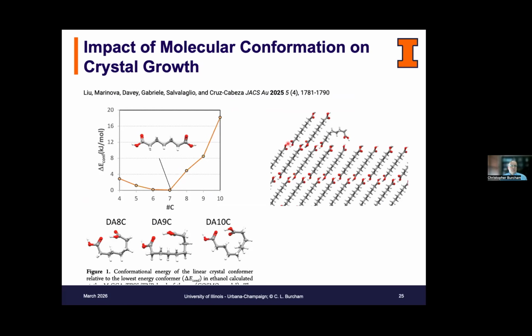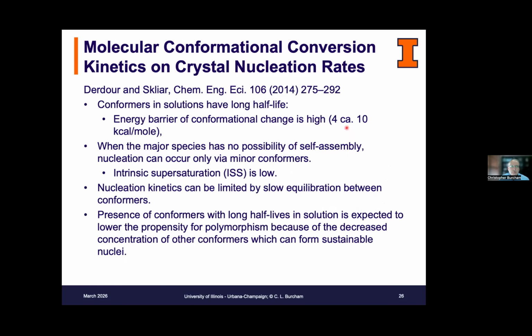More recently, Cruz-Cabeza's group, along with Salvalaglio, have shown, for a case where they looked at diacids of various carbon lengths, that the ability to crystallize was greatly impacted by conformational change once the length of these linear molecules reached a critical value of around 7. And here you can see in this particular lattice, you have a nice linear orientation, but when you come in with one of these conformations, in order for this to dock into the lattice, the conformation of the molecule has to change. This is not a new observation.